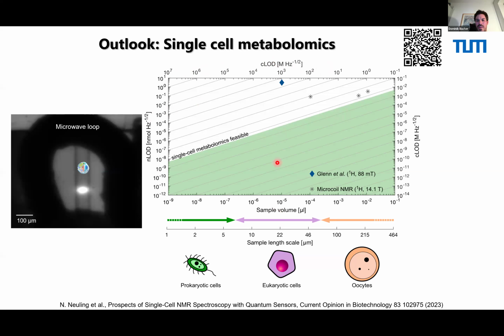So our first experiments, which I did during my postdoc time with Ron Walsworth, would end up here, having this volume of roughly 10 to the minus 5 microliter. This is around 10 picoliter. And we would have a concentration. We measured pure water here, and this ends up in this 100 molar of water, which would basically mean we can detect pure water in a second. So we are far away, of course, from anything like metabolomics, which is marked here in green. So we really need orders of magnitude of sensitivity in order to detect millimolar or micromolar concentrations.